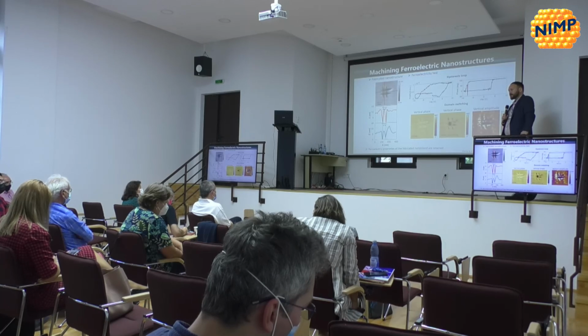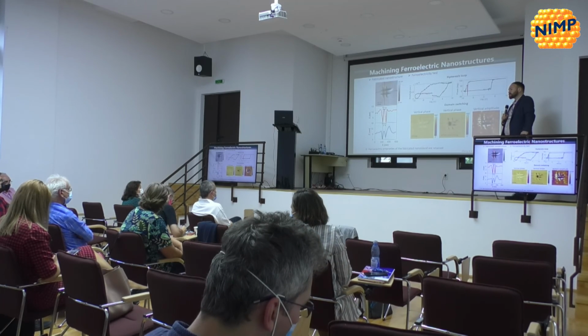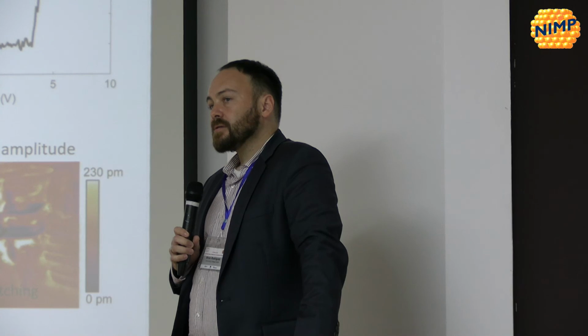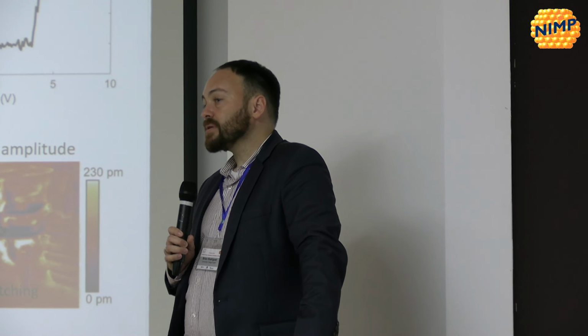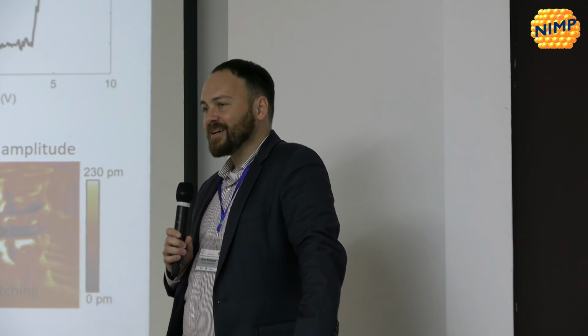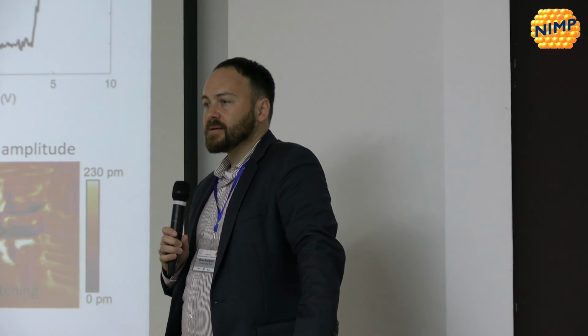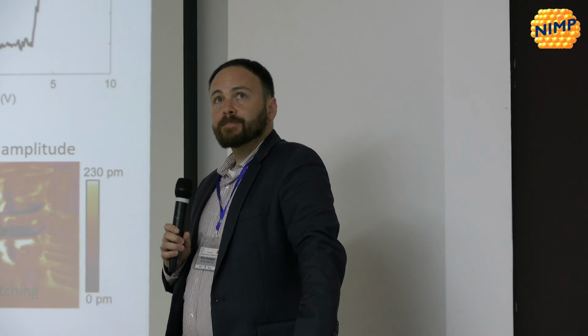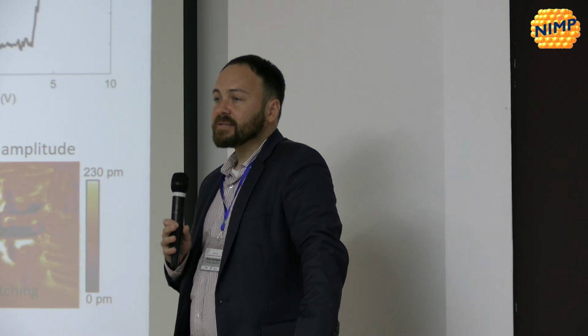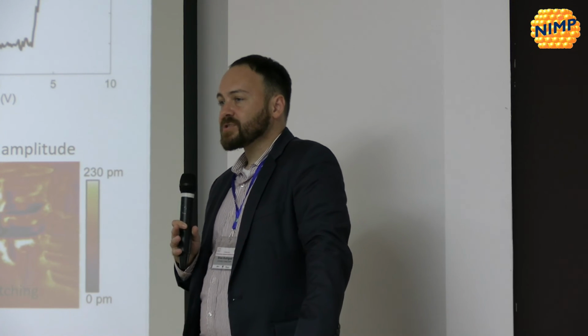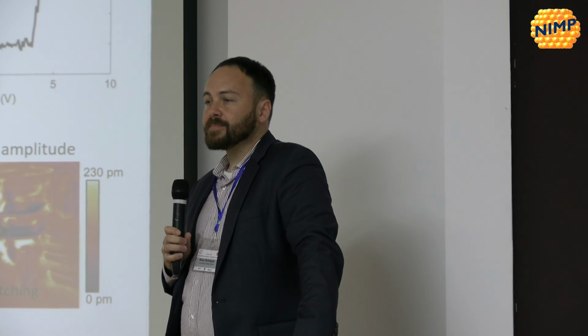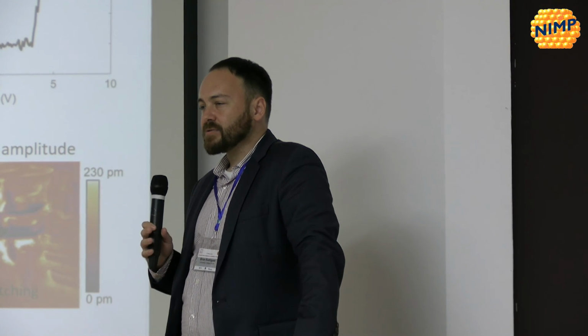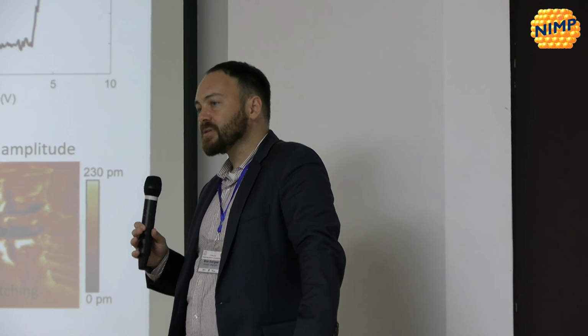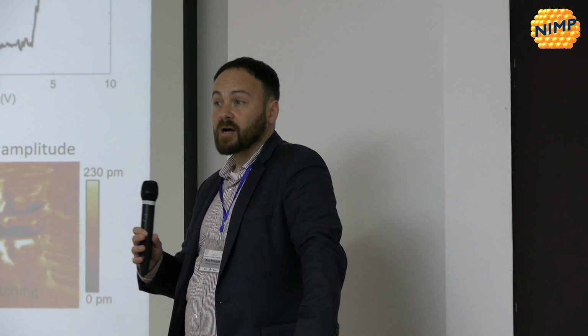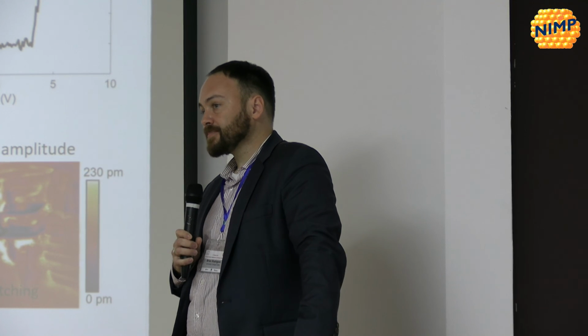Thank you. Did you see significant increase of leakage with the stress? Yeah, the higher the force we applied, the more leakage we saw, but it wasn't completely in line with the force that we applied. The leakage happened at a different voltage than the switching currents, but there was more leakage associated with higher forces. So there's something to be said for a better electrical contact as well, and a larger contact area as we're pushing into the material.